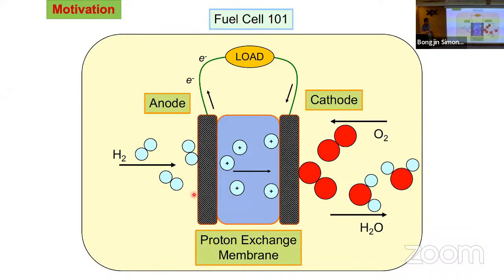So this process is awfully slow. From what I was told, it's about 10,000 times slower than this. So this is actually the bottleneck where all the fuel cell technology comes into play. This cathode requires a catalyst to help this reaction, and platinum is the best so far. And platinum alloy and platinum, clearly, platinum is really expensive. And so the effort is, okay, platinum works well, but still very slow.